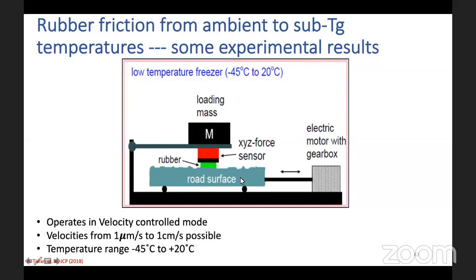So in our experimental setup, we can vary the velocity from 1 micrometer per second to 1 centimeter per second. And we can vary the temperature from minus 45 degrees Celsius to plus 20 degrees Celsius. So we can measure the friction coefficient or friction force as a function of temperature and as a function of velocity.